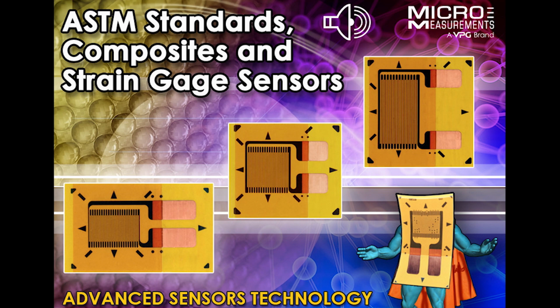By rotating the actual grid and moving the tab to the side, all of that is a lot easier to install. I believe it provides more accurate data because it's more repeatable. It's easier to install, so you do a better job in the install process. Also, that way we can use what the ASTM calls for, which is usually a 125 size gauge for these type tests. You can use a 062 as well. We've done it in some cases. Again, the limitations are usually related to the size of the fibers you're dealing with. Your gauge cannot be smaller than the width of the strand of glass or carbon or anything that you have in your composite. Otherwise, you're not reading properly what the composite is doing.